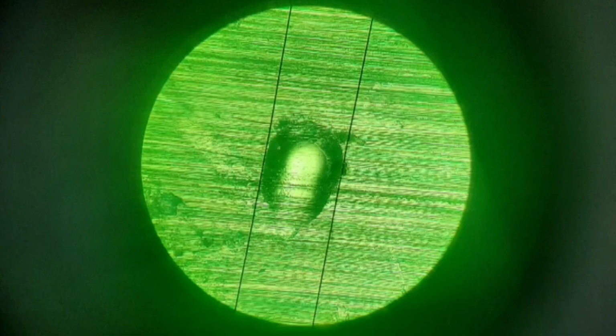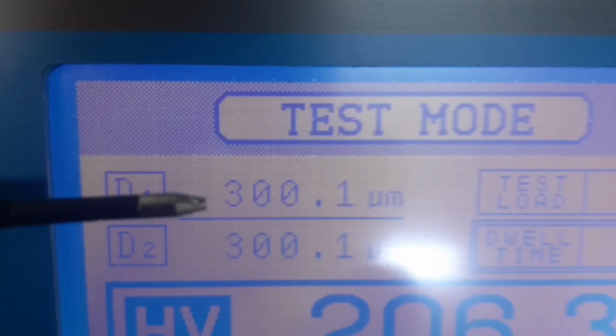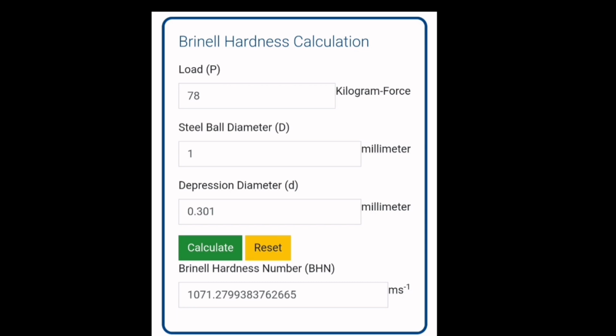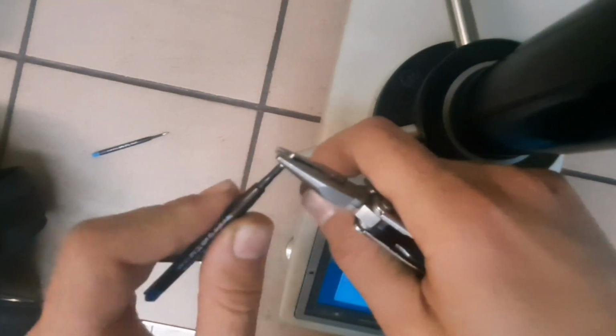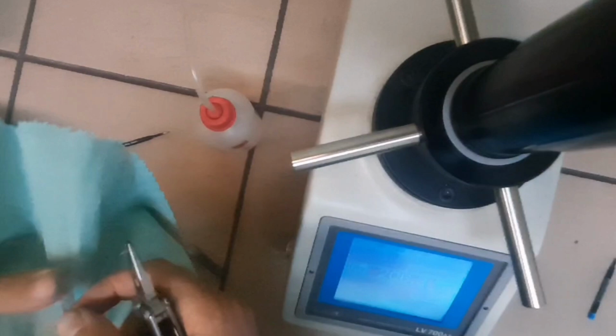It was difficult to balance my weight on this very small ball. That's why I assume the real weight applied was less than my own weight, because the steel plate had contact with the lower plate. The force wasn't transmitted only through the ball. That's why the hardness measurement result will be skewed. I will now use the microscope from the Vickers hardness testing machine to measure the diameter of the indentation. The result of 1070 is way off. It should be around 600. That means that the application of weight has a very large error.